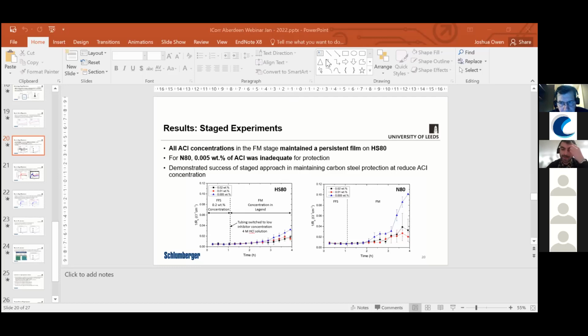I guess we've got a quite high chloride environment in the high strength hydrochloric acid. So I think the hydrochloric acid environment would probably have the most critical influence on any corrosion mechanisms and inhibitor mechanisms. We're probably already working with quite high chloride concentration, if Cl is chloride, not corrosion inhibitor.